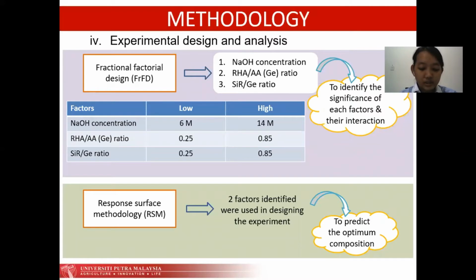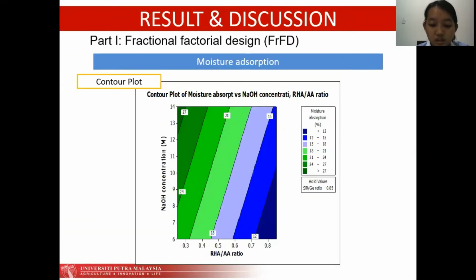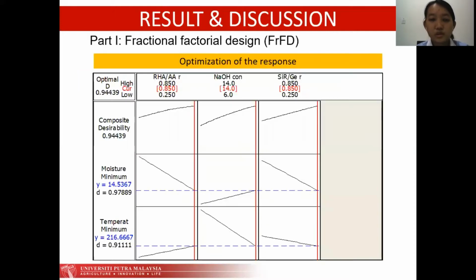This study was carried out using a two-step experimental design, which is FFD and the RSM. There are three factors that will be investigated to identify the significance of each. This is the low level and the high level used to prepare the sample. After that, the RSM is used to predict the optimal composition. It is due to the lower density of the geopolymer with the excess concentration used. So the next,